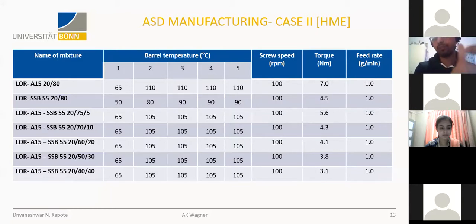And we also tried to extrude it below 90 degrees Celsius, because shellac's glass transition temperature is 36.9 degrees Celsius. For the mixtures of loratadine, Affinisol, and shellac in the ratio of 20-75-5, we tried to keep all the parameters constant and just recorded their torques. And we can see that with an increase in the quantity of shellac, the torque decreased. So we can say that shellac got immobilized quite nicely with Affinisol, leading to the decrease in the torque and increase in the molecular interaction.